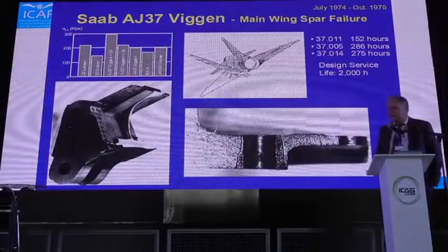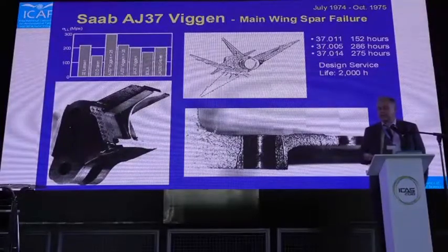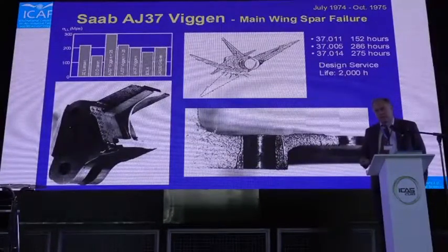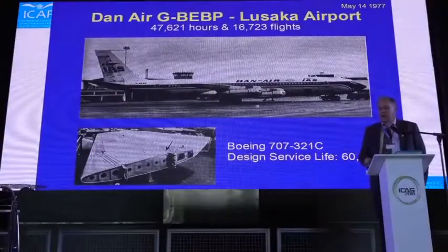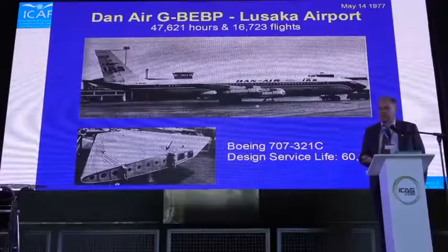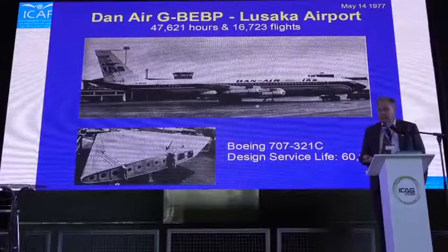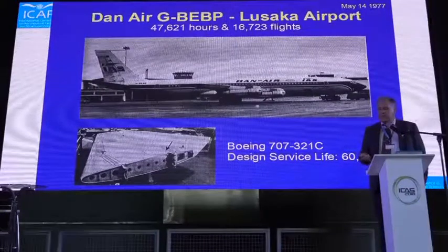We had failures in Sweden also at about this time. These are due to logistical problems. A hole was drilled very close to a free edge, and this was not forwarded back to the stress office. Very simple to analyze when you know, but it's a logistical error. Another one happened in the late 70s. It's a Boeing 707, which crashed upon landing in Lusaka Airport in Zambia. And the design service life here is 60,000 hours, and as you can see above, it failed much earlier.